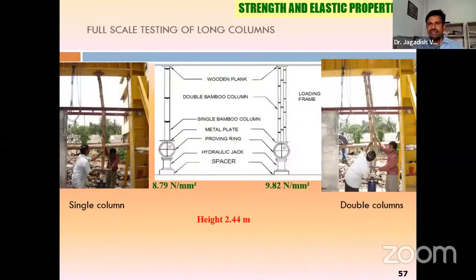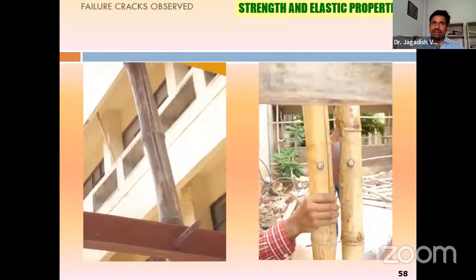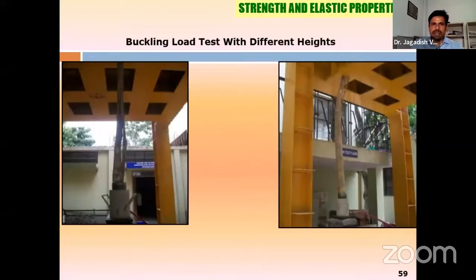Typically, a 7 feet bamboo of 4-inch diameter with a wall thickness of 12 to 15 mm can take a load of half a ton, 500 kgs, with a minimal deflection. This is what we observed. And also the cracks observed, you can see the typical thing.